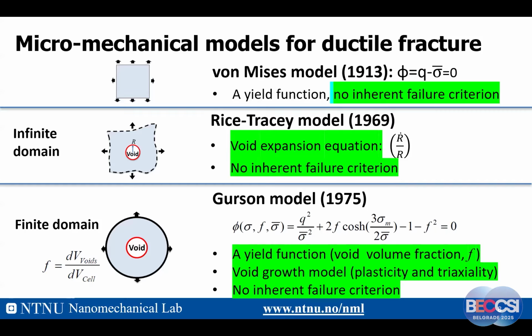Then let's go to the Gurson model. Gurson shrinks the infinitely large medium to a finite medium. Then you have a void volume fraction instead of void radius. So you have V cell over V, and void over V cell. So you have F, and you have a yield function as well. And this yield function is interesting. Gurson's yield function considers the effect of void volume fraction. That means if you have a large void volume fraction, it's easy to yield. If you have a lower void volume fraction, it's difficult to yield. And the Gurson model can calculate the void growth. So it's a yield function itself, but it can consider the void growth model. But unfortunately, there is no inherent criteria as well.